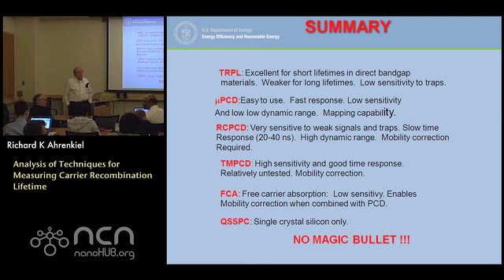Right. So initially, you have this rapid decay due to the surface. And as time progresses, your minority carrier concentration begins to decrease. Most of them begin to recombine and disappear, and then you begin to worry about the trapping effect, shallow traps. Then I'm wondering, in this case, does it make sense to do a two-photon generation technique? You inject lots of photons into your sample, so while you're avoiding the front surface recombination effect, you also sort of saturate the traps. So your decay will be just your bulk effect, without the trap effect.